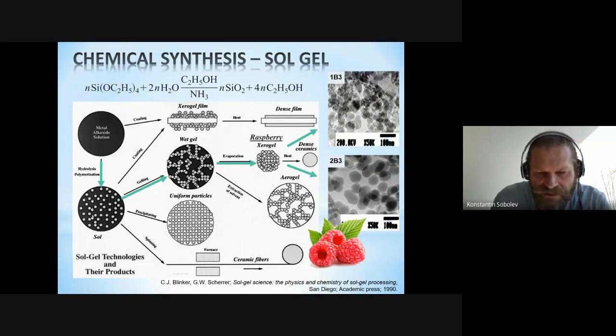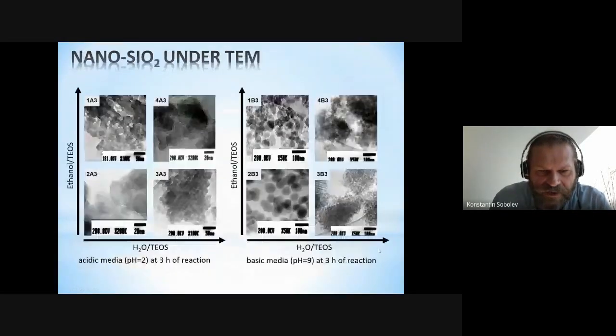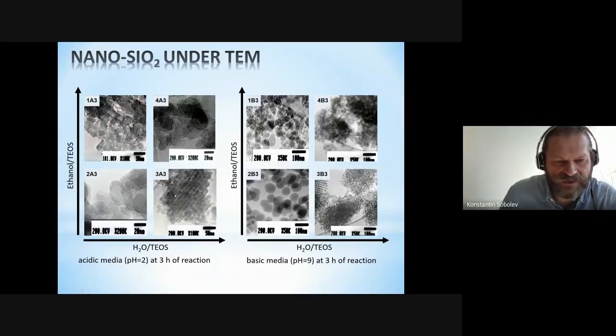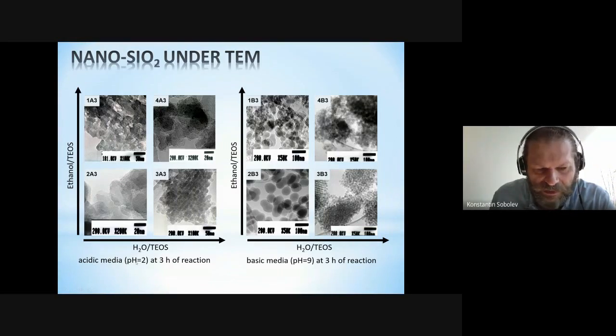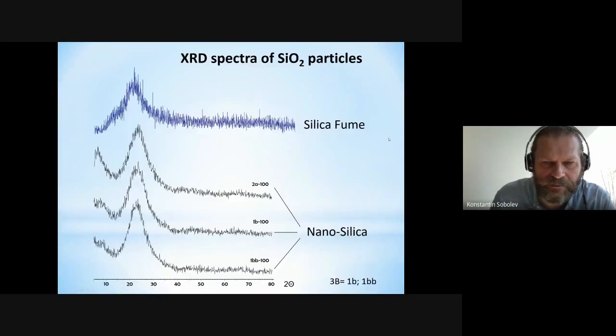I think this direction is very interesting, and there are some works on this. But we tried xerogel, and we were trying to produce xerogels which can be easily dispersible. You can see that by changing the conditions of the experiment, specifically the water to TEOS ratio or ethanol to TEOS ratio, and also varying the acidic media, like pH of the reaction, or basic media from 2 to 9, you can create larger particles, or you can create extremely small particles. Based on our results, both pH values were beneficial to produce the particles. Important was to produce those particles at the highest dilution rates, so particles were smaller and also easily separable for consequent application in concrete.